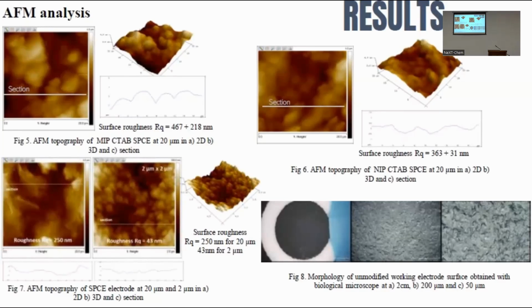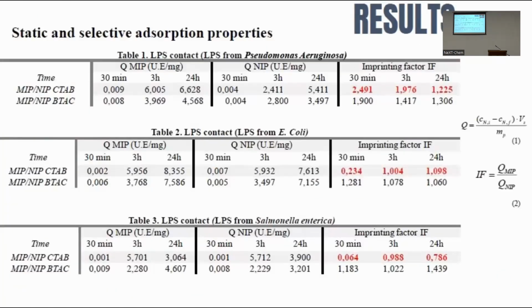The MIP sensor presents a higher surface roughness equal to 467 nanometers with a standard deviation of 218 nanometers compared with their non-imprinted homologue, due to the specific formed cavities. Also, it can be observed that small particles are almost uniformly distributed on the surface of the carbon paste formulation, sustaining the same results. Data collected from the binding properties were evaluated in batch condition for both series of MIPs and NIPs regarding the absorption capacities and imprinting factor, and are listed in tables 1, 2, and 3.